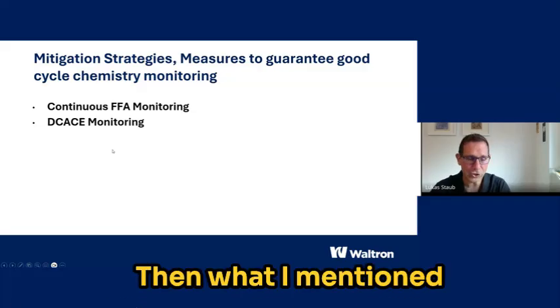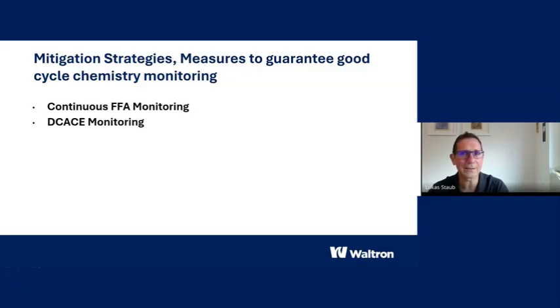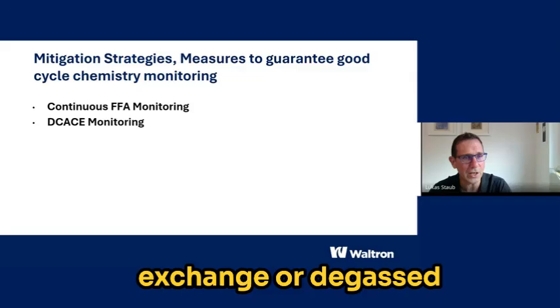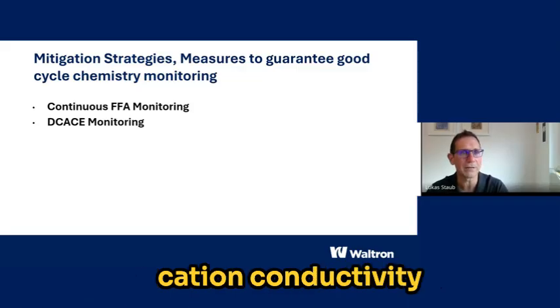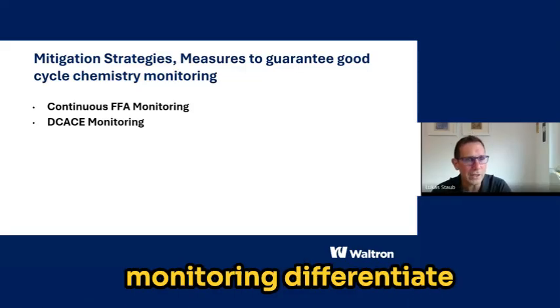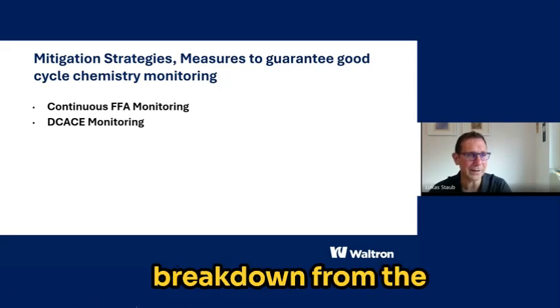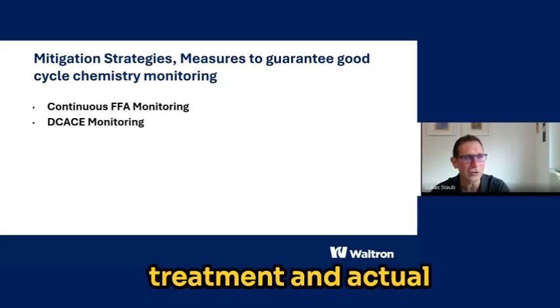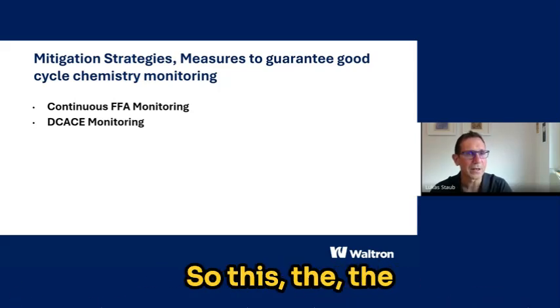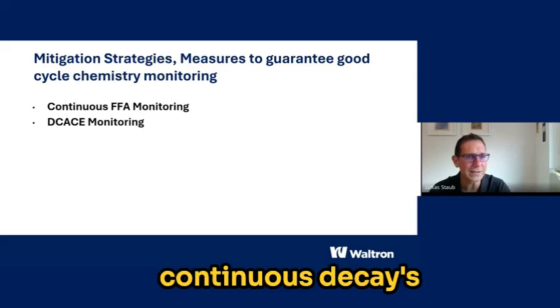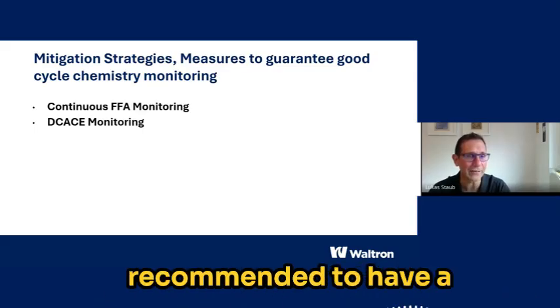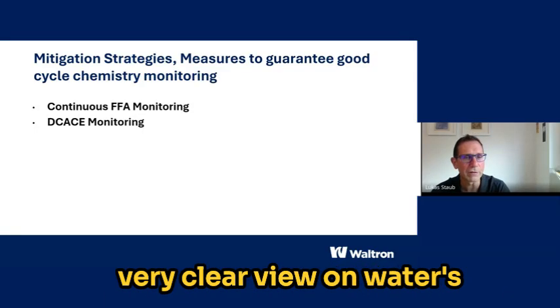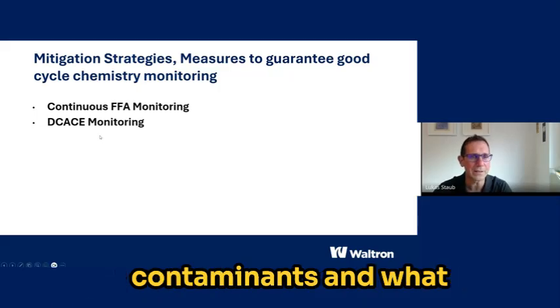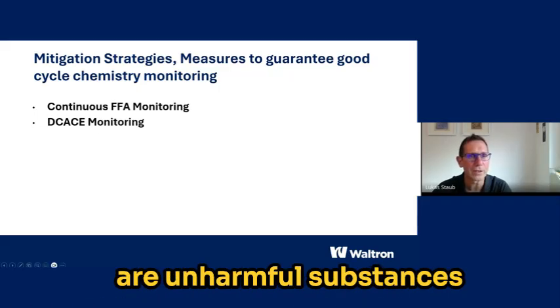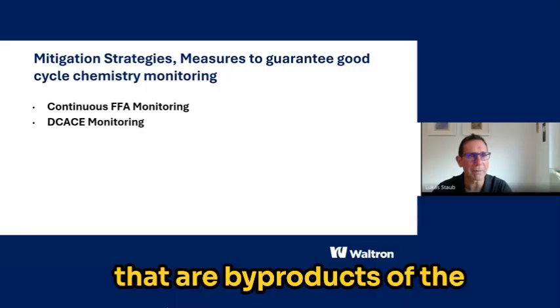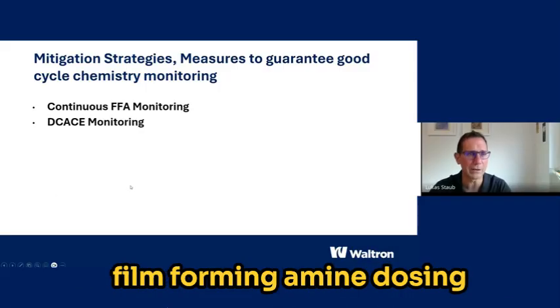Then what I mentioned before, the degassed conductivity after cation exchange, or the degassed cation conductivity monitoring, differentiates between organic acid breakdown from the treatment and actual harmful impurities. So the continuous degassed cation conductivity monitoring is highly recommended to have a very clear view on what are contaminants and what are unharmful substances that are byproducts of the film-forming amine dosing.